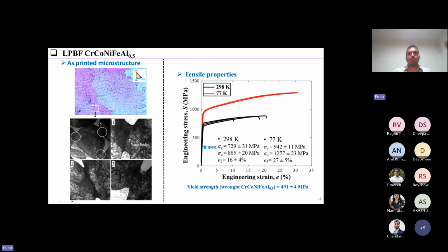And at cryogenic temperature, the yield strength almost reaches 1 GPa. So this is a significant improvement, about 50%. And this improvement in yield strength happens because now you have the cell boundaries decorated with B2 phase and these nano bridges of dislocations. So during early plastic deformation, they are able to resist dislocation movement out of these cells. And essentially these cells have this Hall-Petch effect that is giving you such high strength, and still you are able to maintain a good amount of plasticity even though you have improved the strength of this material.